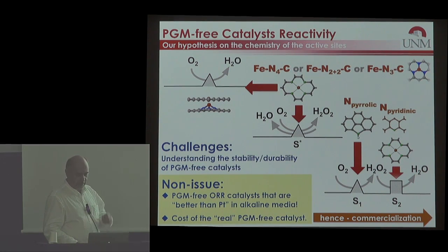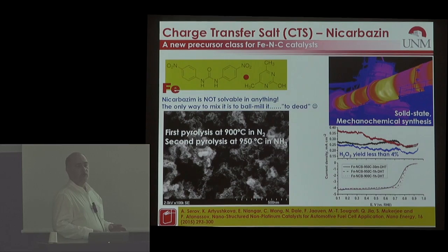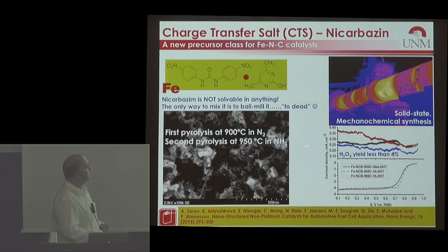To do that, we need to actually have a practical catalyst. And the practical catalyst doesn't necessarily come from your cleanest catalyst. It comes from the catalyst that is made from an amine that decomposes at the highest possible temperature. So we chose this charge transfer organic salt called Nicarbazin as a source for our practical catalyst, because we hypothesized that in order for the material to be stable, it needs to decompose at the highest possible temperature. That was just a working hypothesis.